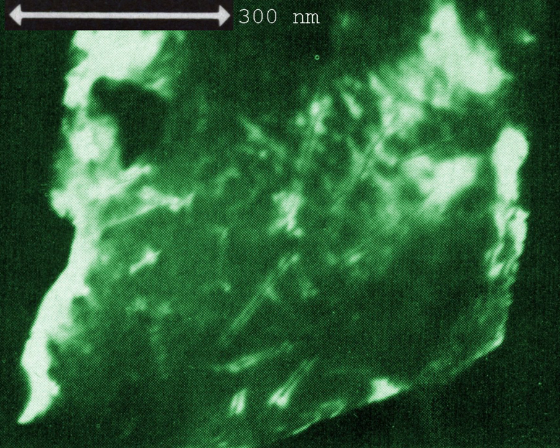When a swift heavy ion penetrates through a solid, it leaves behind a trace of irregular and modified material confined to a cylinder of few nanometers in diameter. The energy transfer between the heavy projectile ion and the light target electrons occurs in binary collisions. The knocked-off primary electrons leave a charged region behind, inducing a secondary electron collision cascade involving an increasing number of electrons of decreasing energy. This electron collision cascade stops when ionization is no longer possible. The remaining energy leads to atomic excitation and vibration, producing heat.